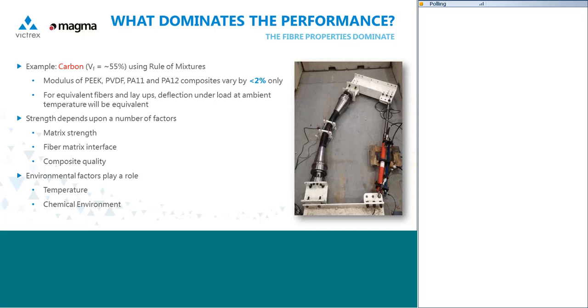Where things do begin to differ is where we're talking about the strength of the material rather than its stiffness. Strength is very strongly related not only to the strength of the matrix itself and the fibers, but the fiber matrix interface. As I pointed out a little earlier, PEEK has a very unique fiber matrix interface, and I think it probably is unique amongst all of those other composite options you can see there. Also, of course, the strength depends on the composite quality. You want to ensure that the quality of the PEEK composite you're receiving is high enough to manufacture what you need. Most importantly, again here, the environmental factors on the composite.